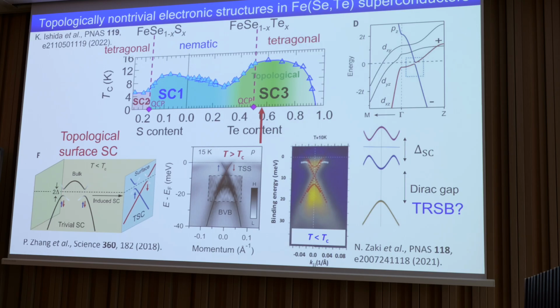Then, more recently, what happens is that if you go into the superconducting state, this topological Dirac cone gets gapped. This is an indication that you may actually have a time reversal symmetry breaking, which creates this gap.